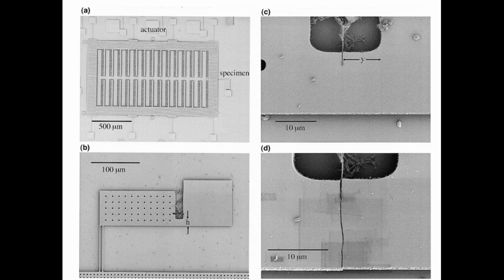Definitely. Oh, and they also cleverly included a microstrain gauge on the chip itself to measure any remaining internal stress in the polysilicon after it was released from the substrate. They found it was pretty low, about 12 megapascals plus or minus 5. Okay. Now, something else I noticed in the paper was about debris. Leftover photoresist getting stuck in the cracks during fabrication.